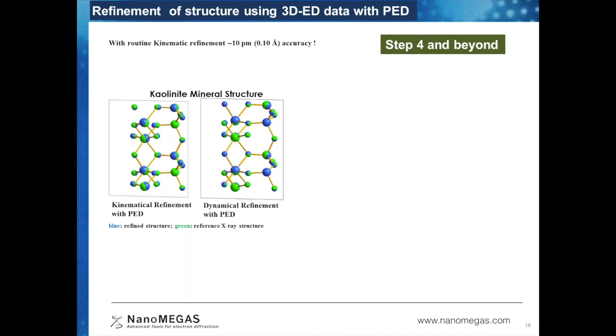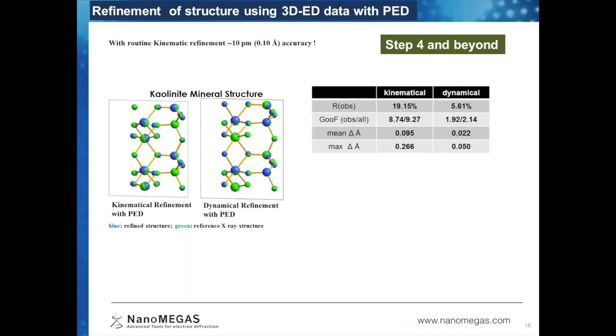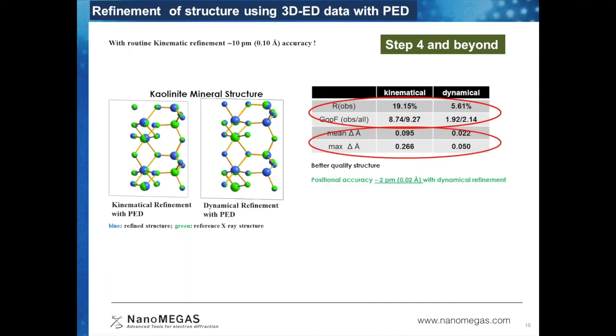These mineral structures were refined kinematically and dynamically against the precession electron diffraction data and compared with the X-ray result. The first thing you can see just by looking at the image is that, once you do dynamical refinement, there is a better agreement of the refined structures with the X-ray structures. Now let's look at some of the numbers to better understand the quality of the refinements, because we always look at numbers to understand our structure solutions. The R factor obtained in the dynamical refinement is much lower than in the kinematical refinement. That means we have obtained a much better quality structure, and the positional accuracy has also increased. Now the positional accuracy is close to 2 picometer, instead of 9 or 10 picometer in the kinematical refinement.